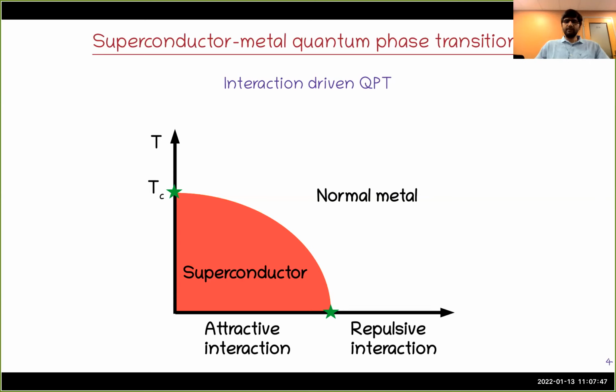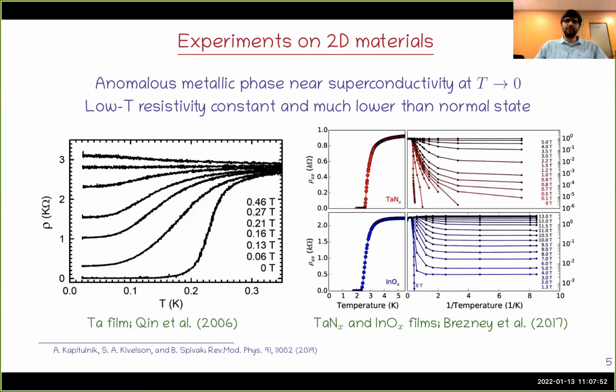But there are actually some two-dimensional materials where something interesting happens. Let me show you some experimental plots, which were the motivation for our work. These materials observed something anomalous. This is a metallic phase, characterized by the property that it has a very low resistivity at low temperatures, but it doesn't become superconducting. Its resistivity is not 0, it's some constant, but it's much lower than what you would expect for a normal metal. Let me walk you through these plots.